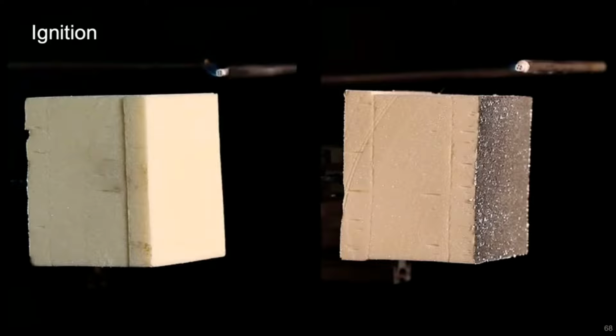I'll explain now what we're going to see. We will observe the formation of a layer of char over the surface of the sample on the left-hand side. This will result in a gradual reduction of the flow of flammable pyrolysis gases through the front face of the sample, and this will result in a reduction of the severity of burning, and eventually the flame will become intermittent on the surface and may even go out briefly.